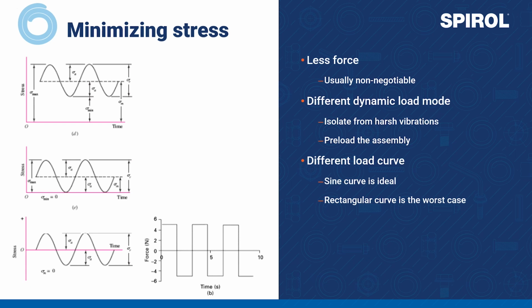What could be done, however, is changing the dynamic load mode by isolating the assembly from harsh vibrations and preloading the assembly. The principle of preload is widely used in dynamic applications. The coefficient that determines the endurance limit is most favorable with a pulsating force, which is the one up here, as opposed to an alternating force. The load curve also plays a role. A sine curve is the most gentle on the application, whereas, for example, a rectangular pattern is essentially a series of repeating shocks and impacts.